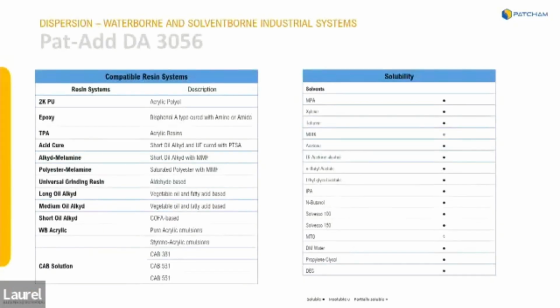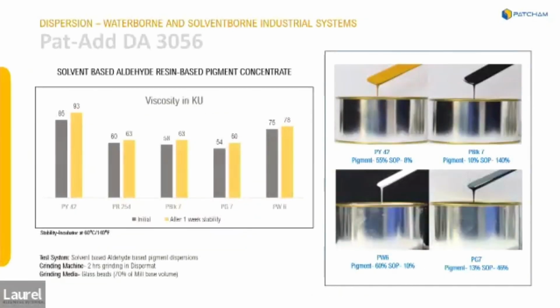Now, the requirement for dispersant, just step back in levels of presentation. Here are the requirements for dispersion. It has to disperse the pigment and keep it stable. That's given by its name. It has to be soluble and compatible in the system that you put it into. So that means in solvent-borne industrial coatings as well as waterborne industrial coatings, that dispersant has to be soluble and compatible and provide that stabilization of resistance to flocculation until the coating is solidified enough not to be mobile. That's the requirement for dispersant. Always keep that in mind. That's always been the challenge.